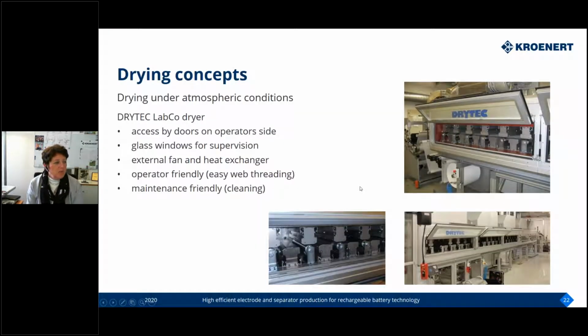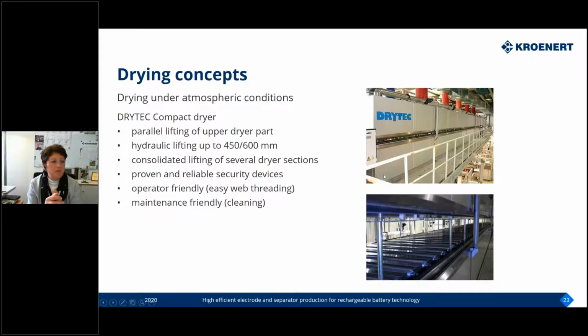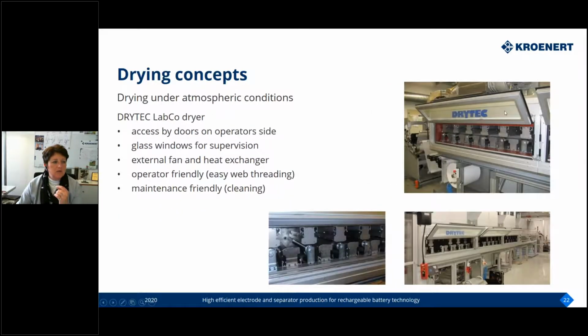When we look into the drying process, to dry a battery coating layer, it's a very sensitive process because you have a very thick layer and you need to avoid drying too fast in order to avoid that the surface starts to crack. And here, for sure, we can handle lab equipment, which you see here, drying equipment in 500 millimeter working width, or we can handle also drying equipment for working widths between 1 meter and even wider. For the small lab equipment, we go into a dryer system where we have a door in front at the operator side, because it's quite easy to handle the dryer from that one side.